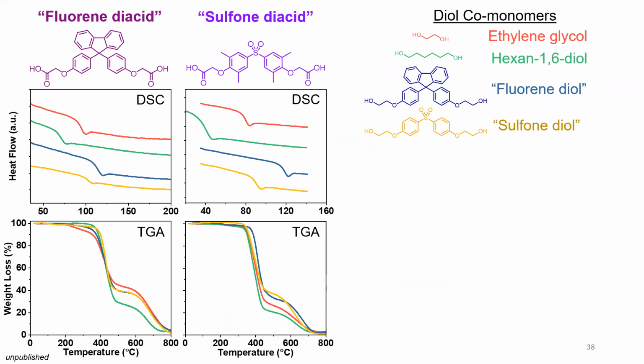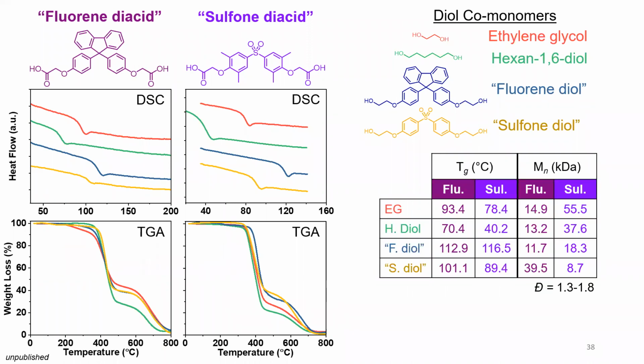But one thing that was nice and convenient is you can see that the trend for the glass transition temperature is similar for the different functional groups. So the ethylene glycol is higher, the hexane 1,6-diol is lower, the fluorene is higher, the sulfone is lower. But overall, when you use the sulfone version, you shift to a lower temperature. So those Tgs are overall lower, even though they follow the same or a similar trend. And then when you look at the thermogravimetric analysis, they both can withstand very high temperatures, around 350, almost 400 degrees, until they start losing 10% of their weight. That's kind of a standard measure.